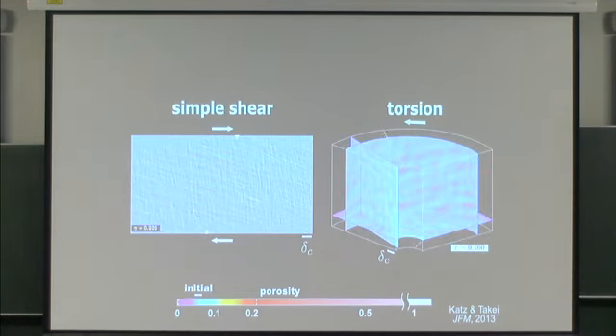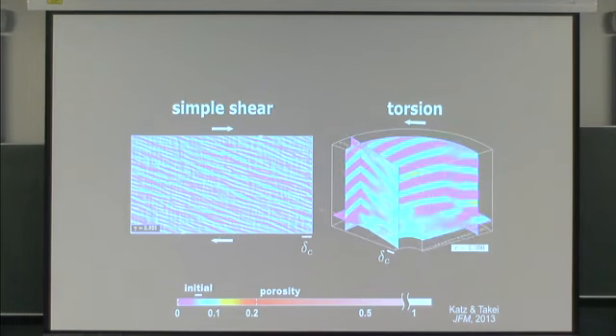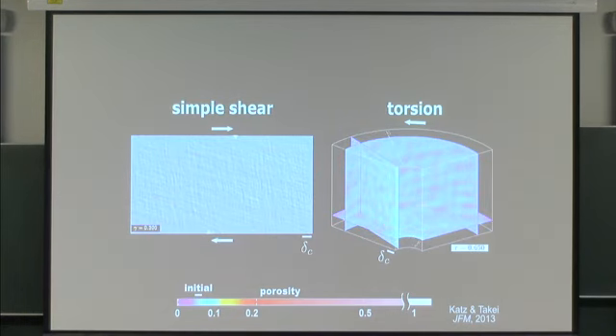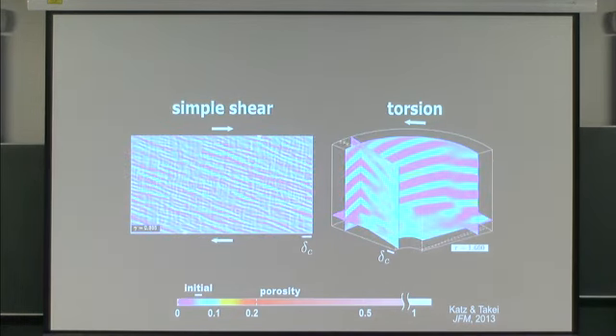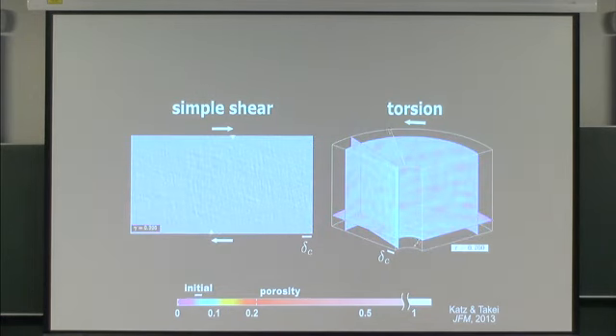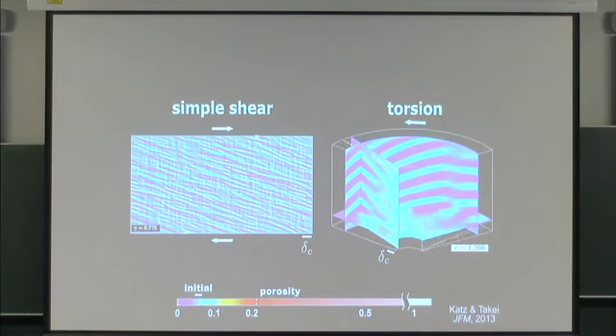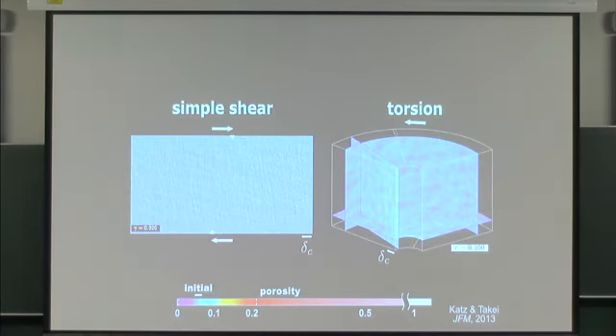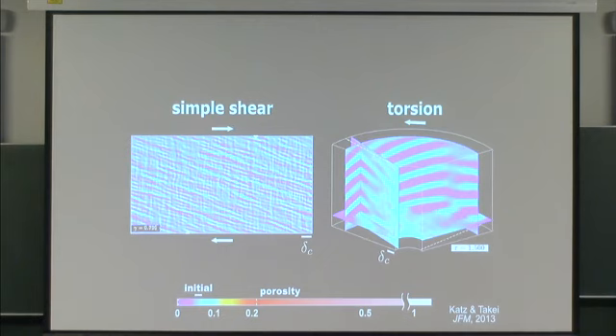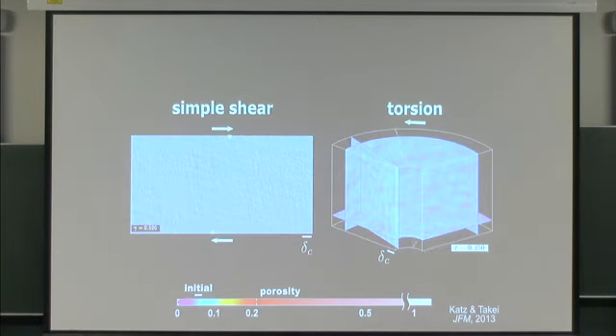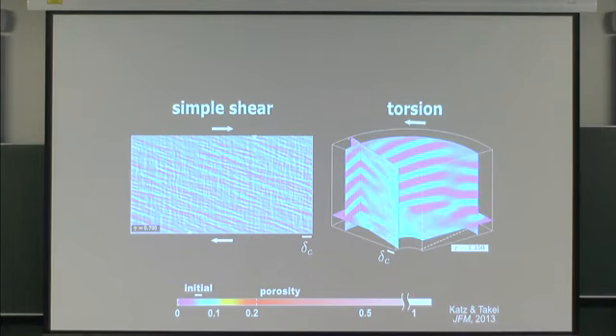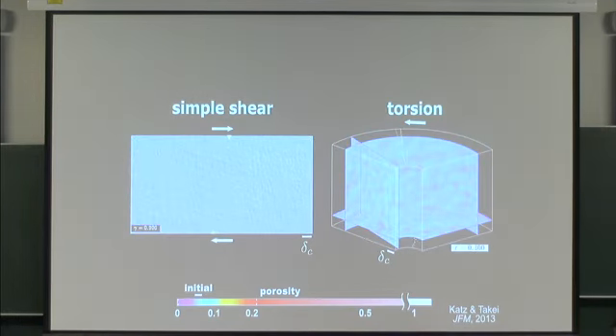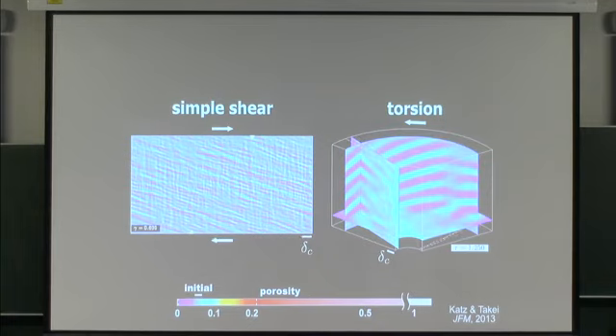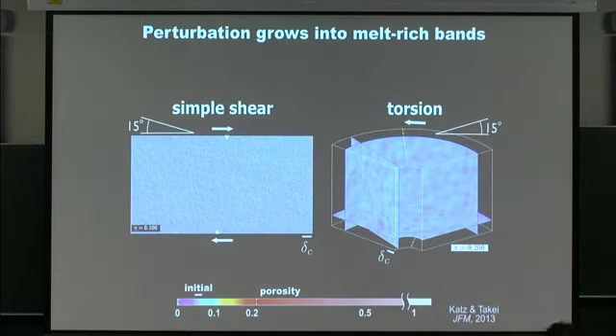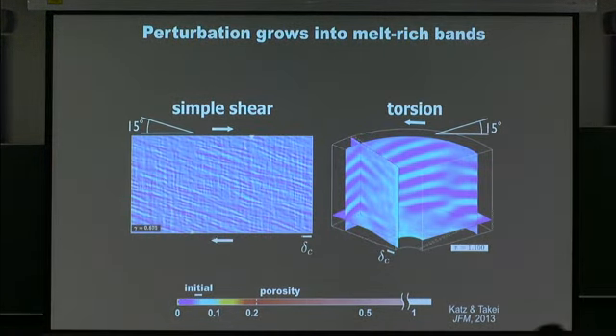And that seems really great, except that there are real problems here, like why do experiments have bands that are only about 20 to 25% porosity no matter how large the strains are, whereas in these models you can run them and the porosity will continually get larger. So there are challenges in understanding what physics is missing from the models to reconcile that once again.